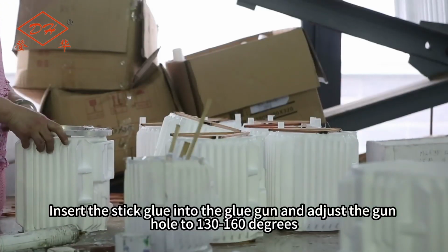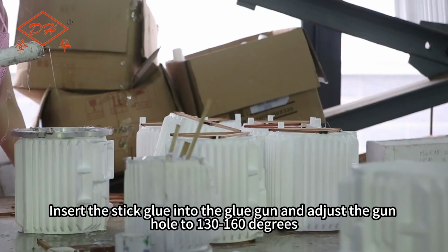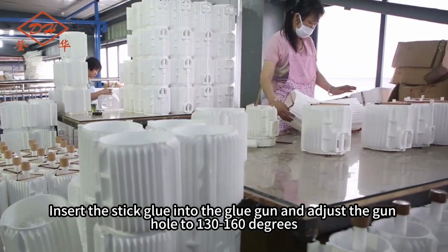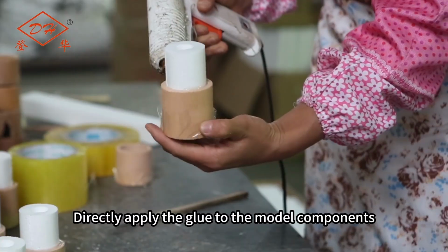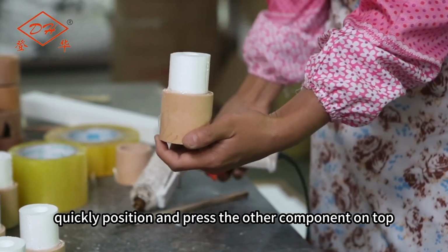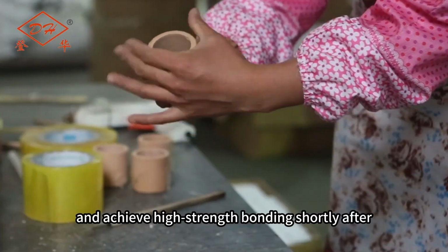Insert the stick glue into the glue gun and adjust the gun hole to 130 to 160 degrees. Directly apply the glue to the model components, quickly position and press the other component on top, and achieve high-strength bonding shortly after.